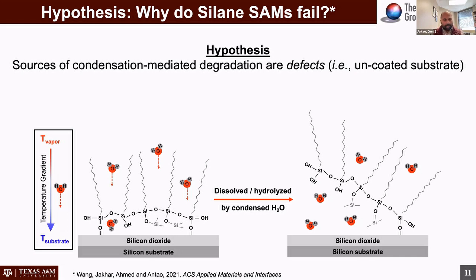And so based on that understanding, we said that our hypothesis was that the sources of condensation-mediated degradation are defects. And the defects here we define as uncoated sections of the substrate, which result from the presence of water in the system. If you think about these silane-coated surfaces in the surface chemistry literature, they say if they make them right, they last for years on end. You can do contact angle measurements or ellipsometry measurements and XPS measurements on them 2-3 years down the line. If they're just sitting in ambient conditions and there's nothing wrong with the surface, it looks as pristine as the day they were made. But we try to understand why during condensation do they fail so quickly.